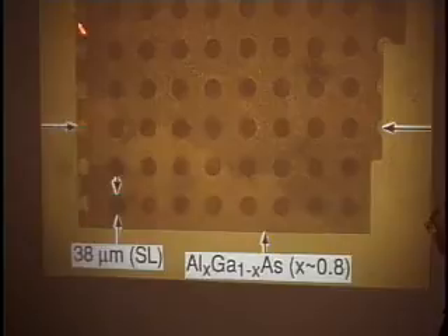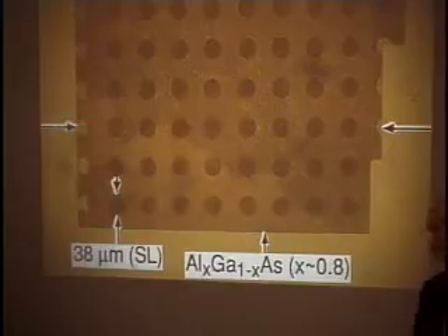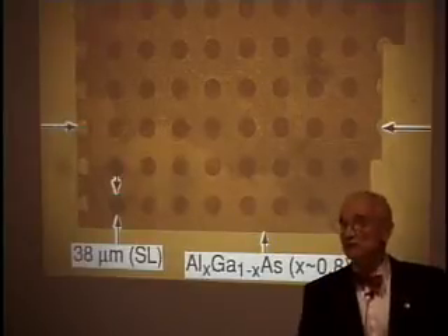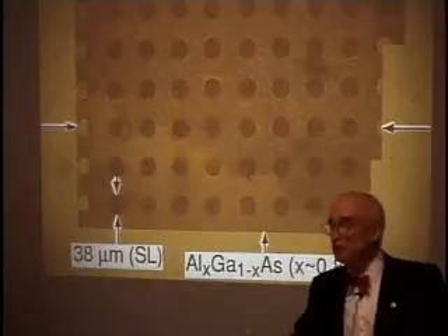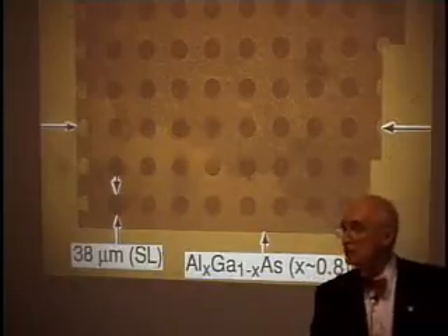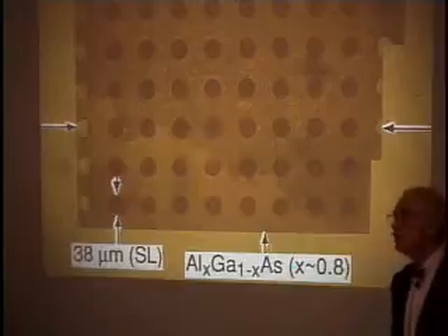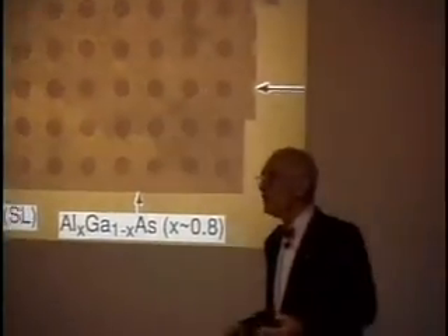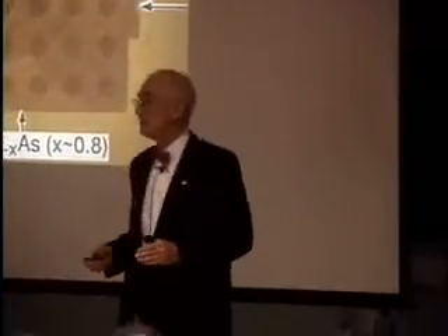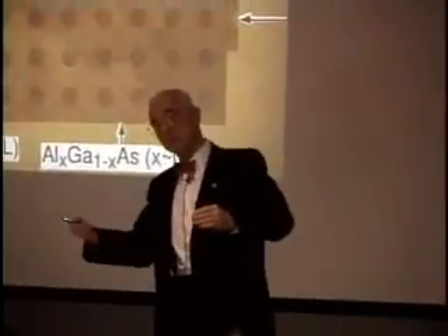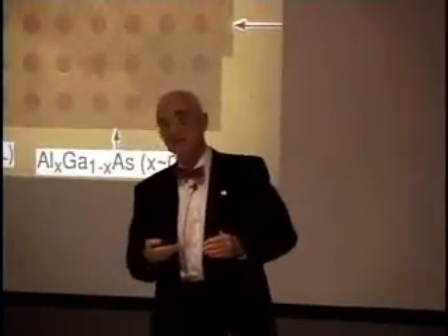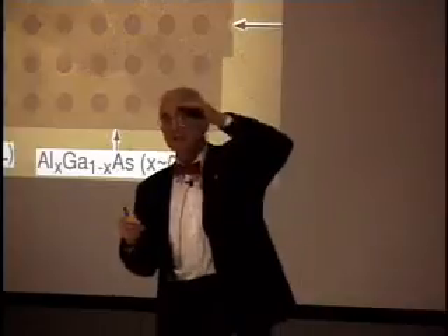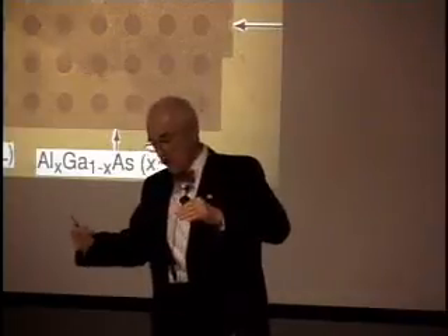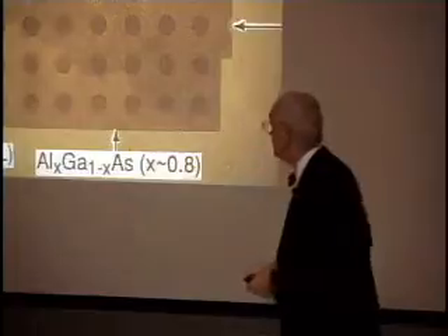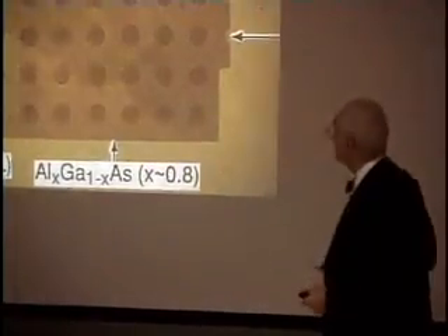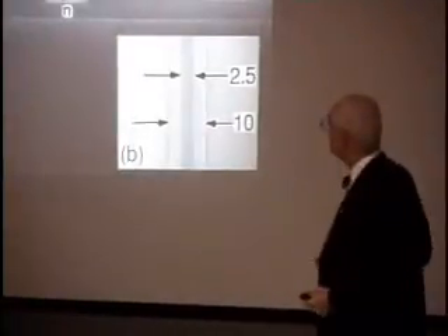But where we have cracked into the edge of one of the superlattices, the oxidation is fast in the aluminum arsenide, and it goes laterally underneath. So from day one, we knew about subterranean buried oxides. You can't do that with silicon. You don't set up silicon in such a way that you have an edge oxidation. But in the III-Vs, we can set things up so we can oxidize down or we can oxidize edgewise. That turns out to be very important. That is another technology for defining devices.